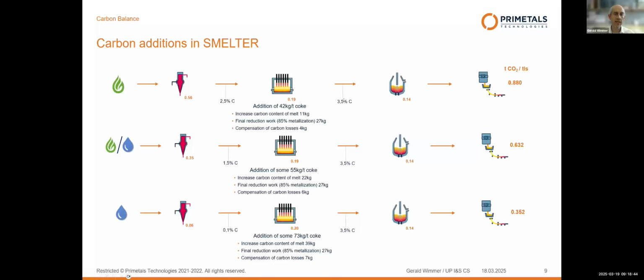Typically, we start about 3.5% of carbon. For a smooth operation, 4% is, of course, easier. And if we consider some 3.5%, then we see we need about 42 kilograms of coke to be added to the furnace. Part of it is used to increase the carbon level of the bath. Part of it is used to make the final reduction. And part of it is, of course, losses because yield is high, but not 100%. And if we in future switch to pure hydrogen production in our direct reduction plant, then of course the DRI has almost 0% of carbon, and consequently the carbon amount that we have to charge to the smelter has to be increased. But regarding carbon level of the hot metal, the smelter is quite flexible, so we can adjust.